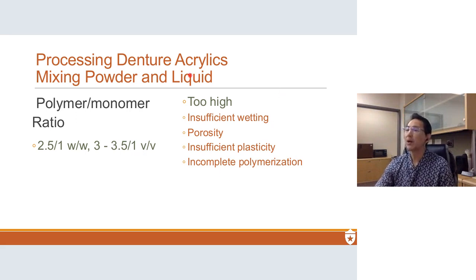Anyway, if the ratio is too high, in other words, you have more polymer than you should, or not enough monomer, then you'll get insufficient wetting because there's not enough liquid to wet all of the powder properly. And that creates porosity because you're going to have voids in between the particles as the liquid wets the particles. You also will get insufficient plasticity because since there isn't enough monomer, the reaction progresses really quickly and you get to a solid state really quickly, and it doesn't give you enough plasticity, doesn't give you enough working time. And you also get incomplete polymerization because you just didn't have enough monomer to polymerize the whole mass.